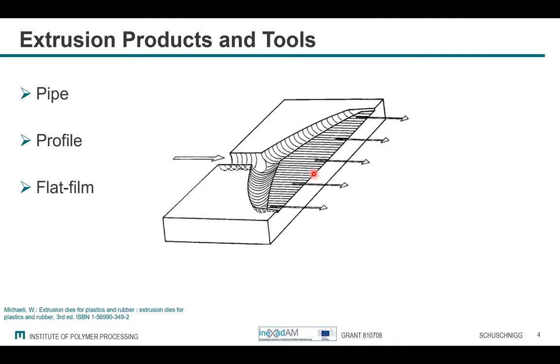And then it's depending on what you are processing. If you are processing a single material all day long and you never change it, then you will have an optimized die for this product, for this mass throughput and for these conditions, and then you can get out an optimized film. If you're changing your materials daily, then you have to have an overall good coat hanger die, which can process most of the materials, but non-optimized.